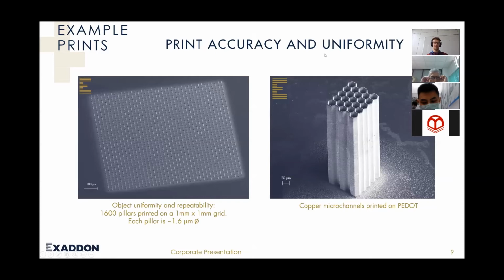At the microscale, accuracy is very important, and uniformity and repeatability is very important, as it should be for a mature technology such as ours. So on the left here, we have 1,600 micropillars printed in a 1x1 millimeter grid. Each pillar is around 1.6 micrometers in diameter, just as a test to show the repeatability of our system. And this can go up to these hexagonal copper microchannels printed on PEDOT on the right there, which, as far as we are aware, is only possible with our technology.